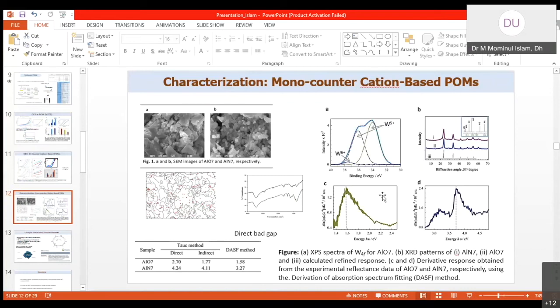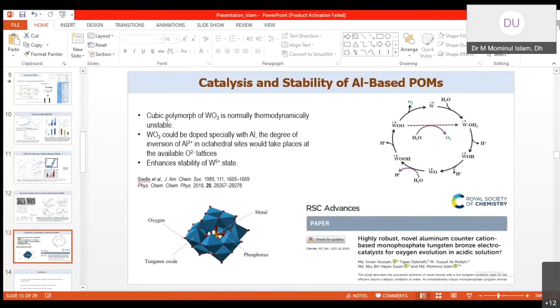And in our experiment, we could synthesize this tungsten 5 state with the help of aluminum. It is known that this tungsten oxide, especially this cubic polymorph, is thermodynamically unstable, but it was also previously reported that if we could replace the central metal with aluminum, it might be possible to design this. This speculation was published in 1989, and recently we worked on this and successfully got this stable compound for the first time. We found that tungsten 5 is very stable in this polyoxometalate, and we followed this up, published this year.